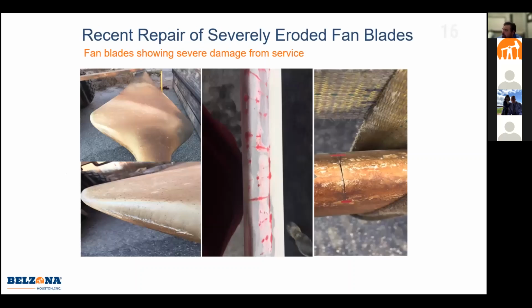This is a recent project we've done with about 12, 14-foot long blades. So as you can see from these pictures, this is the damage. And it really wasn't just the leading edge on these blades. It was almost everywhere on these blades. You were seeing a lot of stress cracks from just being used over time. And you can just see how bad the damage can be.